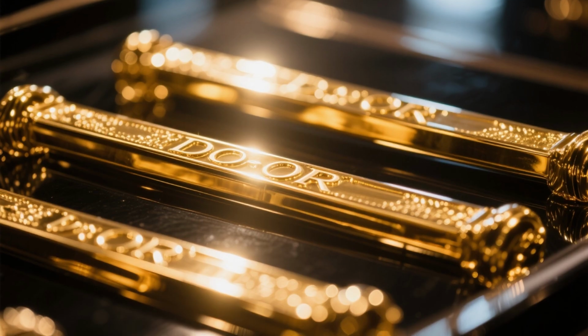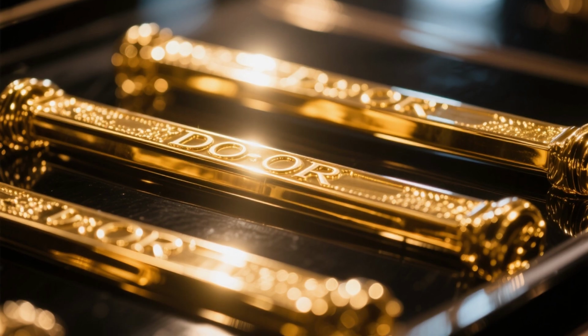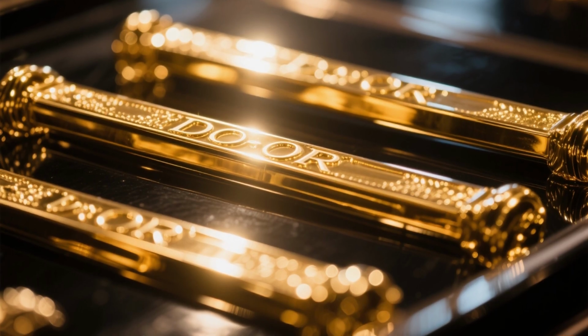These bars look golden, but they're not pure yet. Typically they're about 80 to 90% gold, with the rest being silver and other trace metals. To get closer to pure gold, these doré bars undergo another round of refining, often using the Miller process. The bars are remelted in a special furnace, and pure chlorine gas is bubbled through the molten metal.